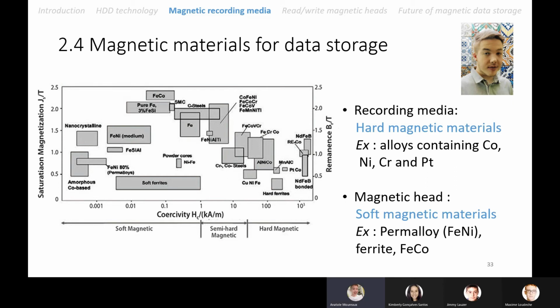So, for our recording media, we'll generally use a material with high magnetocrystalline anisotropy, because if the material has a strong preference for a magnetization along an easy axis, it's usually harder to unintentionally switch its magnetization. This can be explained by a concept we've talked about earlier, coercivity.